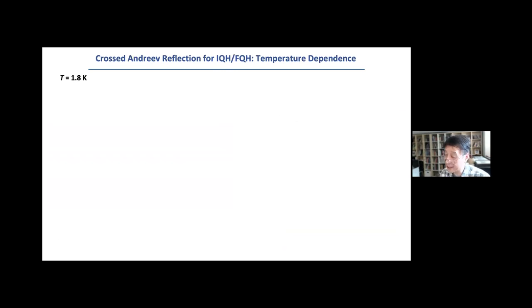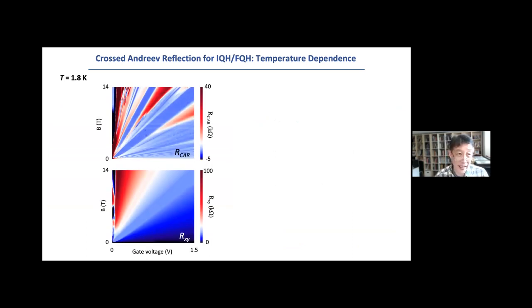So let's look at the data now. With this much higher quality sample than what we made 4 years ago, we can do the following experiment. Already at 1.8 Kelvin with a magnetic field up to 14 Tesla, clearly this R_CAR, which I'm showing in terms of color, with negative signal being bluish, right? You can see that R_XY shows the typical band-like behavior, the quantum Hall Venn diagram, but R_CAR shows many blue stripes, which means that the CAR process is quite strong.